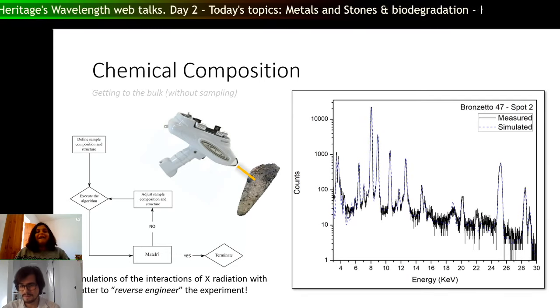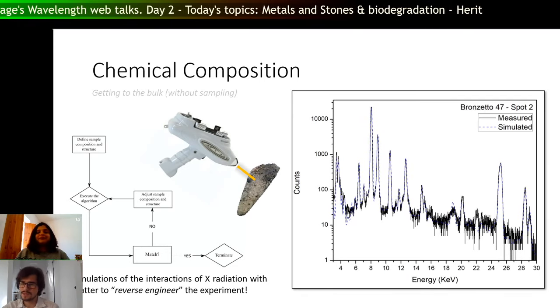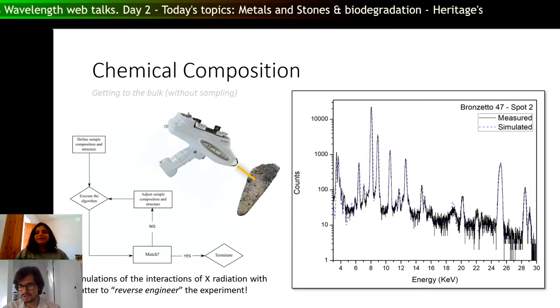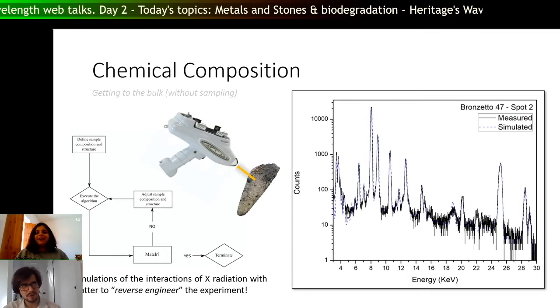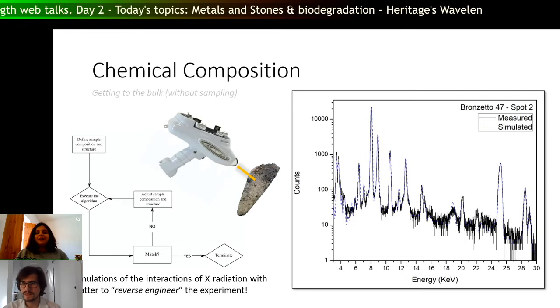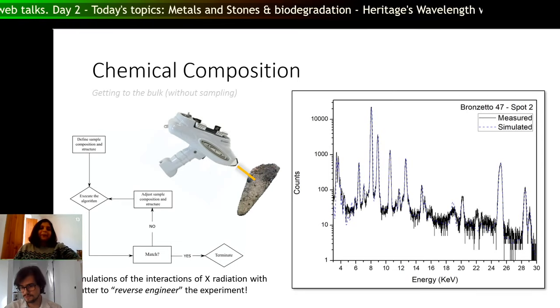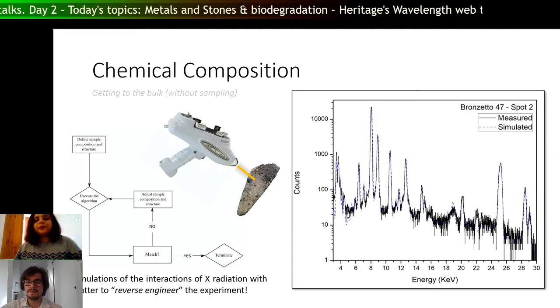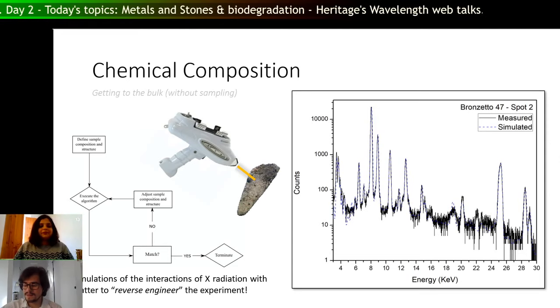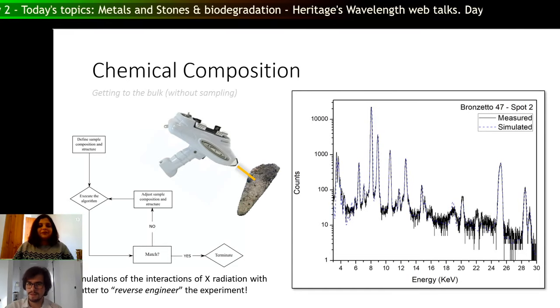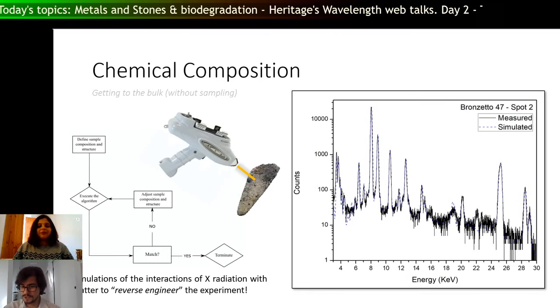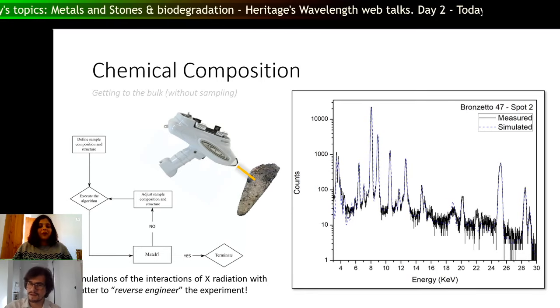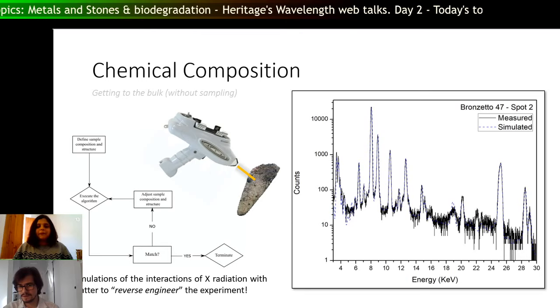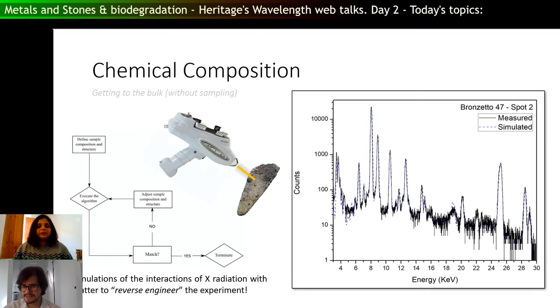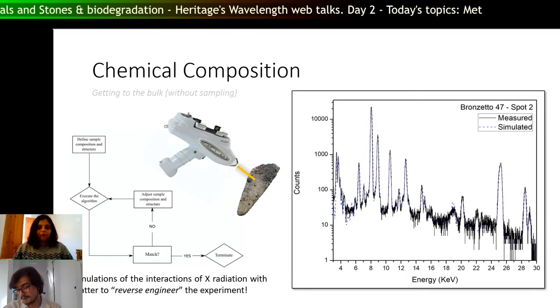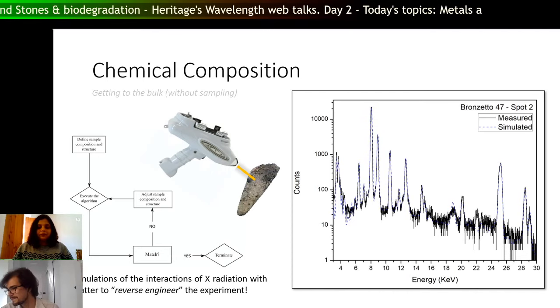There are a series of them. The one I used is the XRMC package. You also have XMI-MSIM, if I'm not mistaken. You have Geant4, PENELOPE. There are a series of algorithms to produce it. And when you have a match, it means that layer ordering, layer composition, and bulk composition that you told your computer could represent reality. So it has been tested with reference samples, and it works. It's very interesting.